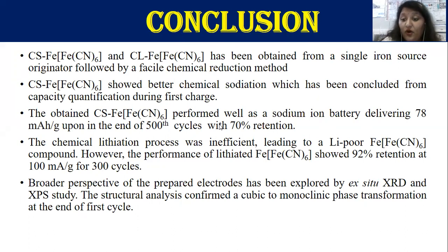In spite of all the disadvantages of Prussian blue analogs, most efforts are focused on sodium-rich Prussian blue analogs. However, there are reports on PBAs with incomplete sodiation. This demands a sodiated anode for practical application, which again leads to several hurdles from the commercialization perspective. On the other hand, our approach was to employ a convenient atmospheric condition synthesis method, which avoids challenges like high pressure or reducing atmosphere to inhibit oxidation.